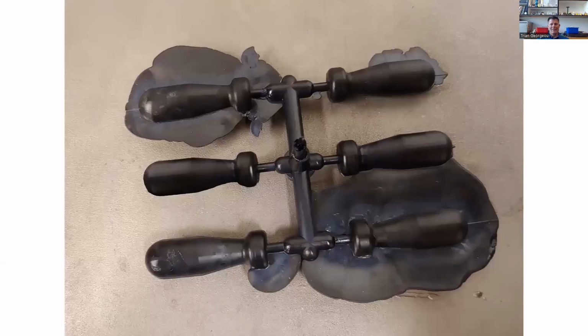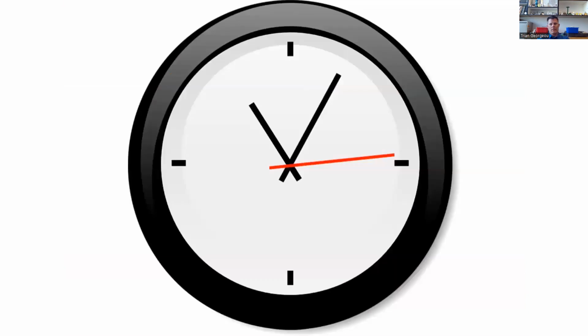In the end, we have an overfill, which results in flash around the parts. Flash is the extra material that crept into the mating surfaces of the mold. There are some usable parts, but again, not all of them are usable. This can be due to many factors such as barrel and nozzle temperature, mold temperature, injection time, injection pressure, and or the cycle time. We will now repeat the process with the proper injection pressure.